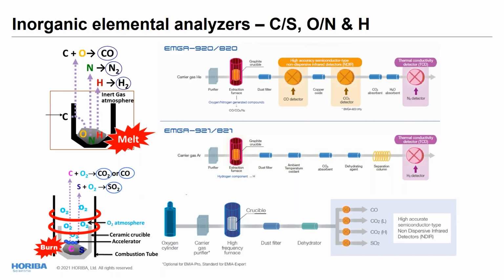For carbon and sulfur, it will be a little bit different. We are using a ceramic crucible that will be placed in an induction furnace with a flow of oxygen. This flow of oxygen with the increase of temperature will create from carbon and sulfur different gases, and we will create CO2, CO, and also SO2. All these gases will flow into the system and will be detected by NDIR detectors. As for XRF, all the intensities measured by NDIR or TCD detectors are proportional to the quantity measured and then can be related to the concentration, making quantitative determination possible.